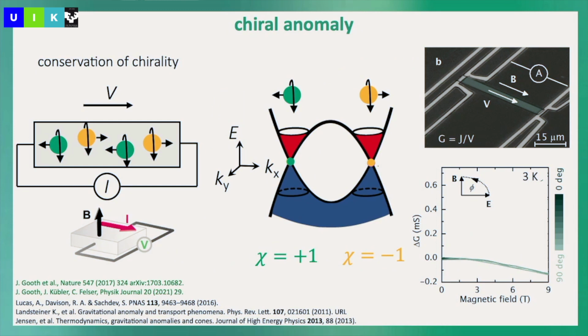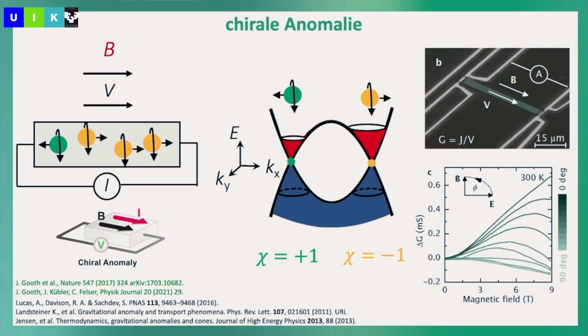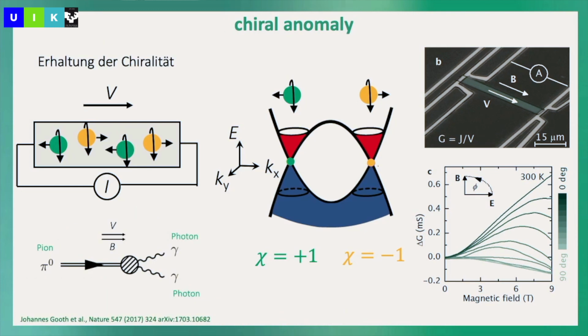Anyway, so here we looked for the chiral anomaly, because here we made very nice nanoribbons to avoid all these measurement problems, okay, and we saw that the conductivity is negative, which means the resistance is positive, if we have the magnetic field and the electric field perpendicular, like in a normal Hall measurement, and then if you turn the magnetic field in the direction of current, you see a giant change in the properties which we think is a chiral anomaly, and which is here simply for the people who are interested, were proposed originally in high energy physics, but nowadays people try to prove the chiral anomaly with heavy ion collisions. So they think in 10 years they maybe can show the high energy version of the chiral anomaly, but it's already done if you want in Weyl semimetals.